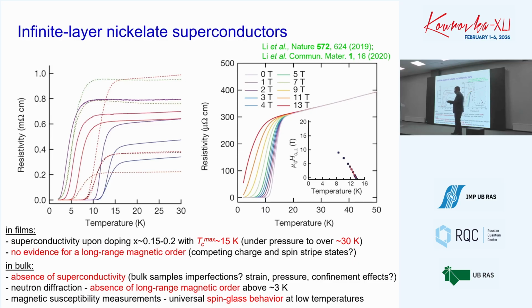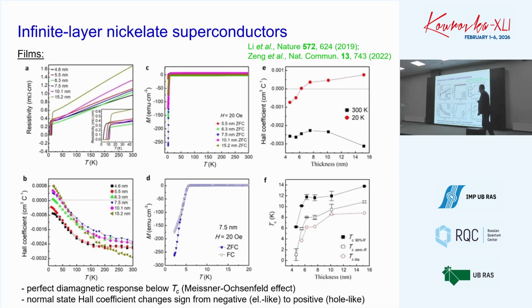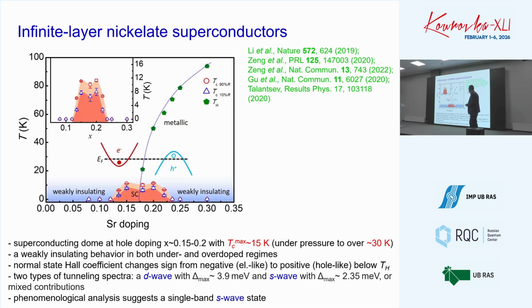systems, and all of them have a square lattice of nickel ions, and this is somewhat unusual. This is just to show that all these experiments were well reproduced, they show perfect diamagnetic response, very clear evidence of superconductivity, and even, similar to cuprates, they show a change from electron-like to hole-like behavior in the Hall coefficient in the normal state, and this is related, if you extrapolate, to the middle of this superconducting dome.